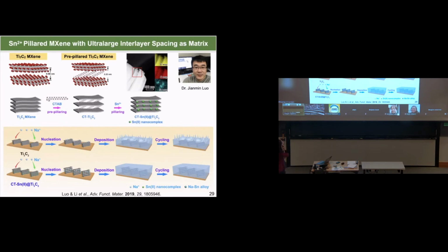In this work, we try to enlarge the interlayer spacing of the MXene material, so we use a surfactant. This is what we call a titanium carbide MXene-based material. It's a two-dimensional layered material, very similar to the structure of graphene. So we enlarge the interlayer spacing and dope it with some tin-based complex. Then, when we do the sodium nucleation and growth, because tin can easily alloy with sodium, the sodium will first plate within this interlayer, and then eventually it can grow around all these MXene islands and realize a very smooth sodium deposition process. Okay.